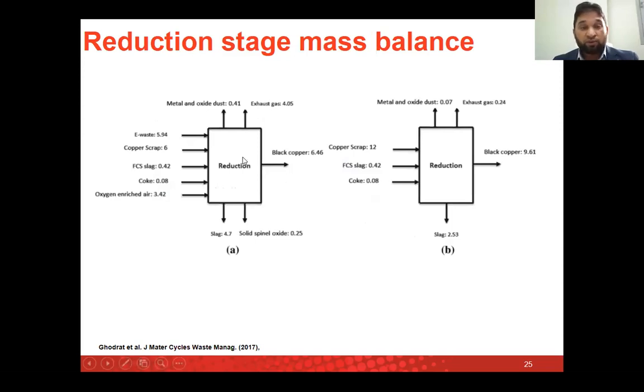Moreover, if we look at the mass balance, I will not go into too much detail, but this gives understanding. If we have one processing unit, how do we do the mass balance of that one? We have the e-waste 5.94. These figures are in terms of tons, calculated using HSC Chemistry, so we give these inputs. Then we have the copper, about 6 tons. We have the FCS slag, like the iron oxide, calcium oxide, silicon oxide slag, 0.42, and then coke 0.08. We have oxygen-enriched air 3.42. Put into the reduction furnace, and then we get black copper, like 6.46.